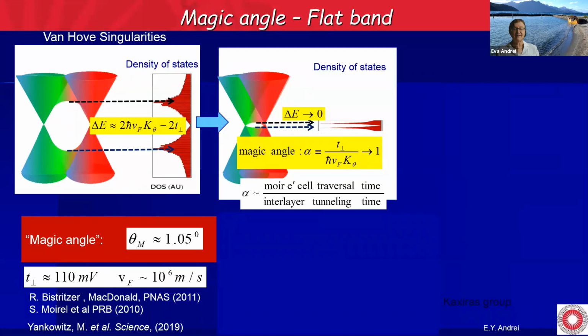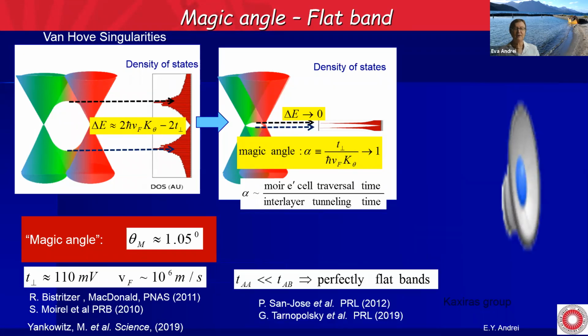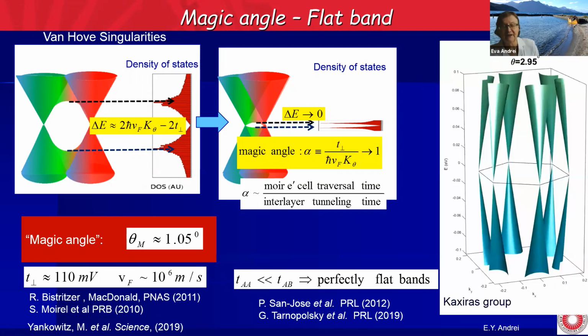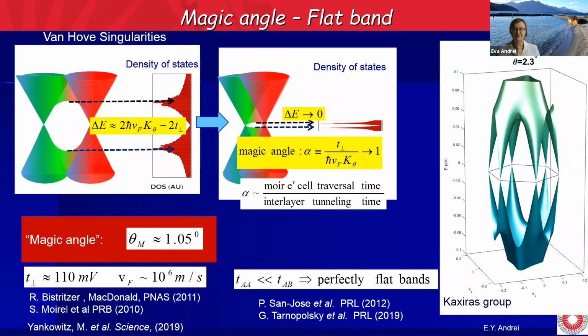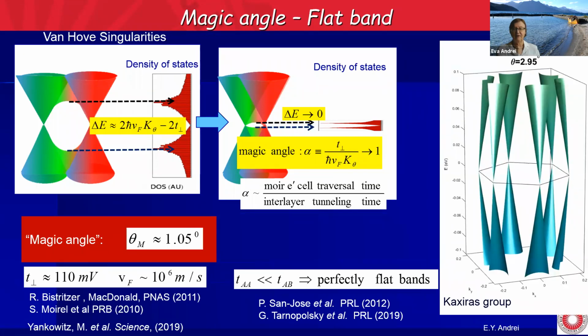Now, this calculation was done by assuming that the hopping is uniform, and it's the same hopping whether you're at AA or AB. When you take the hopping on the AA lattice to 0, you get perfectly flat bands, as was recently shown. And here I have an animation that shows you what happens as you decrease the twist angle, and you see these Van Hove singularities here, or the saddle points. We're approaching the magic angle, and boom, you have a flat band here.